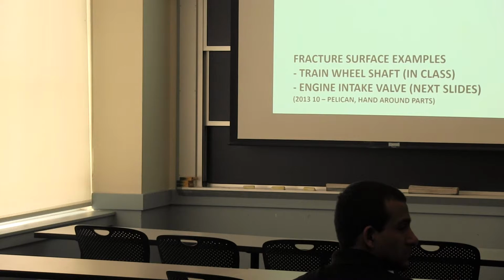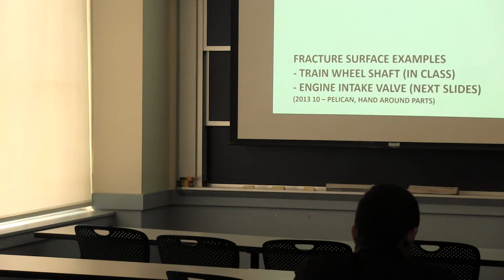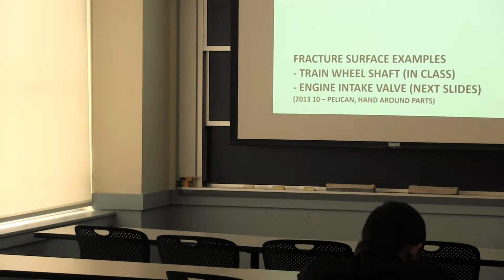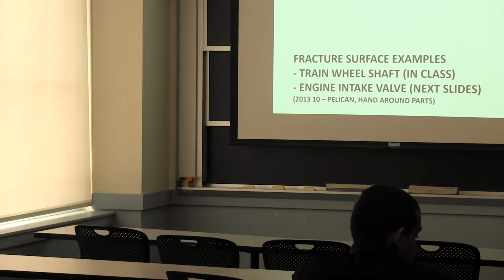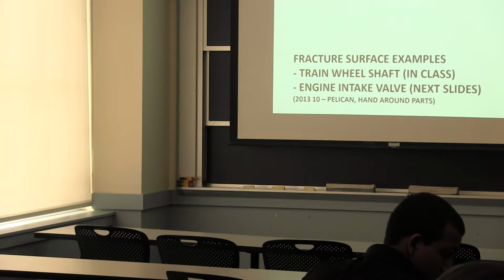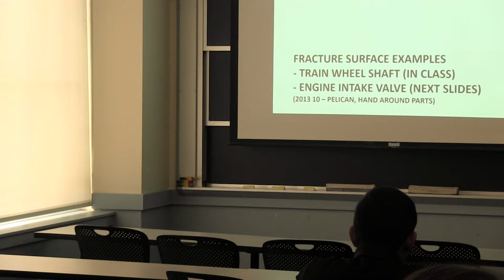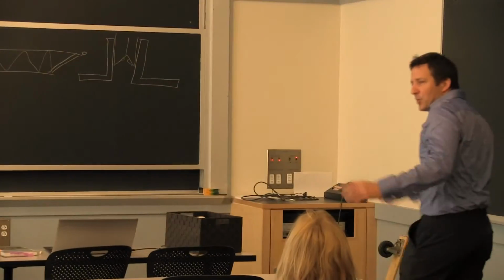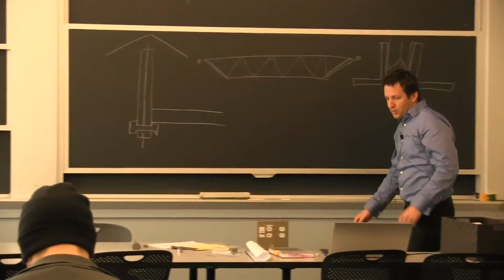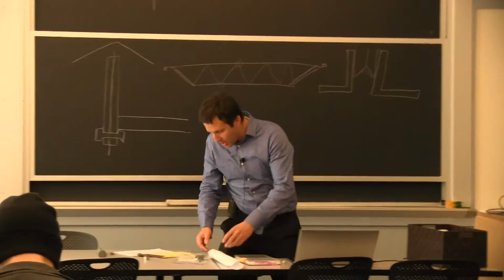Crack propagation line, these big steps over here tell me it all started in this area, and there's another step here, so there was another initiation right there, for example. At some point in time, the crack was just going exactly along these little lines there. So at this point, we've identified at least 3 initiation sites. If we kept looking, maybe we'd find more. What does it mean? Well, it means it wasn't that hard to start a crack. If it started at 3 locations, they were competing to reach the center, so there wasn't just one problem with this system.